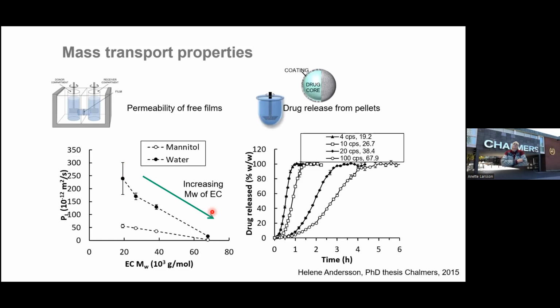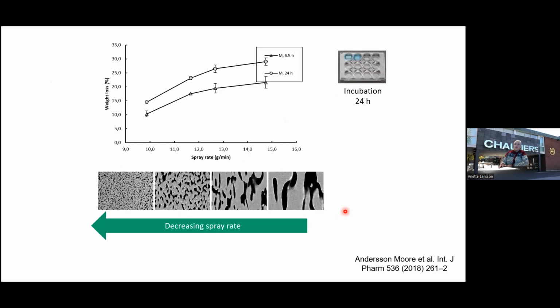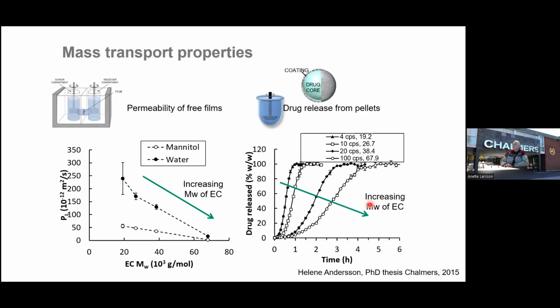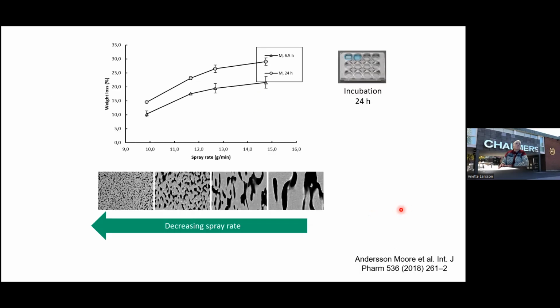And if we then instead take a core system where we have the API here, we can see that when we increase the molecular weight, we get slower and slower drug release rates. So the same phenomenon happens if we have water molecules that should penetrate through the coating, or if it is the drug. And I should say also that in this case, we varied the molecular weight of EC. We did a similar study where we varied the effect of the HPC also.